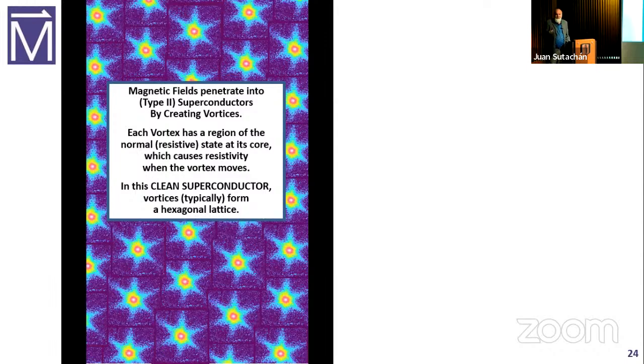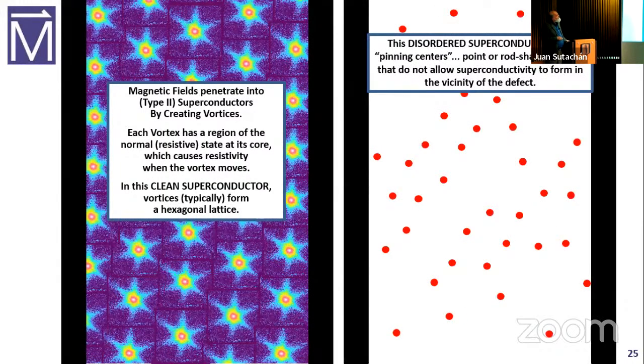But clean superconductors don't work as well for magnets. What you want to do is put in pinning centers, which are defects that are either a point or shaped like a rod that don't allow the superconductivity to form in the vicinity of the defect. So this material may be superconducting, but not where the red dots are. This material is superconducting, but not in the middle of the vortices.